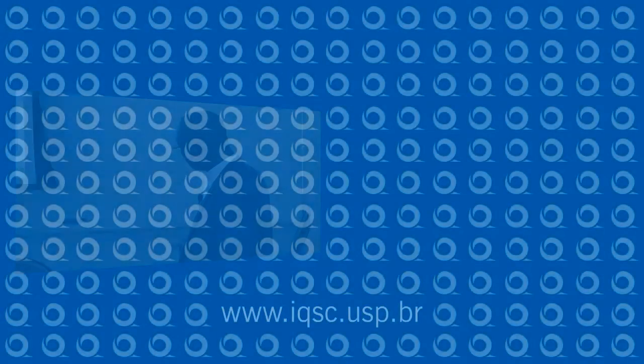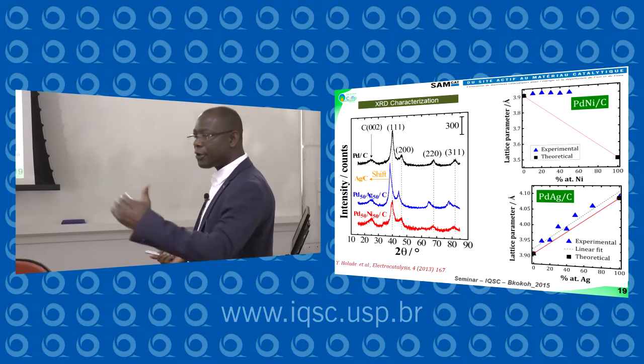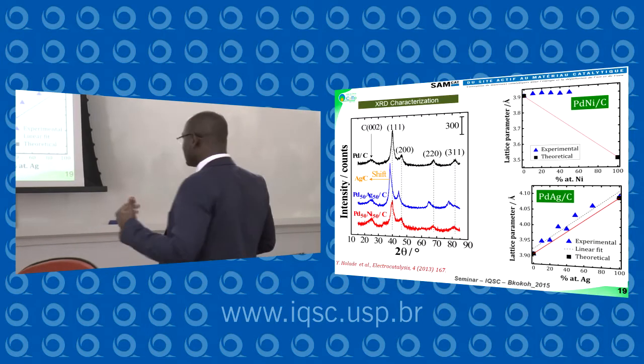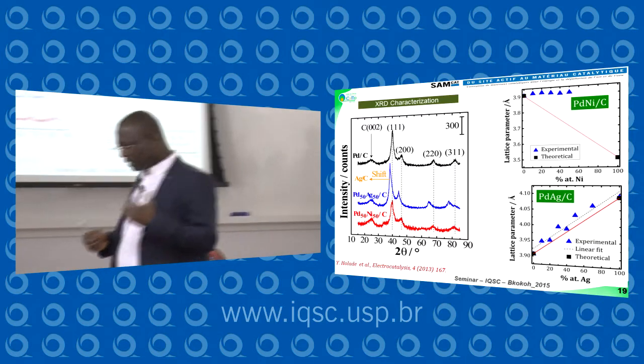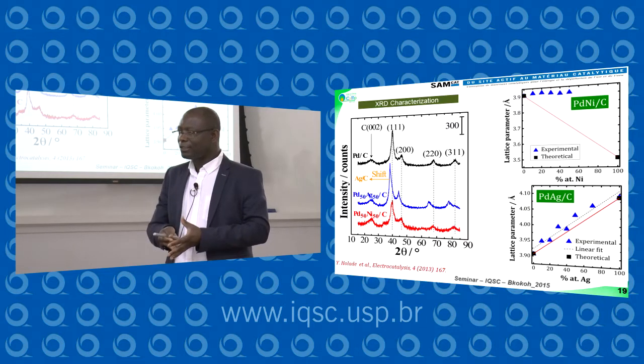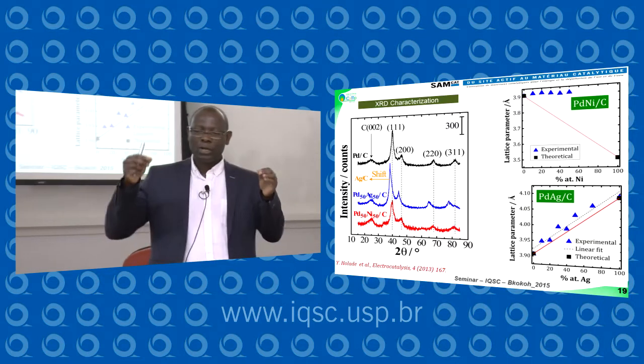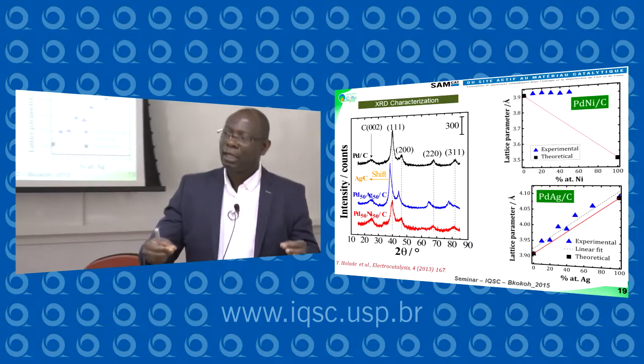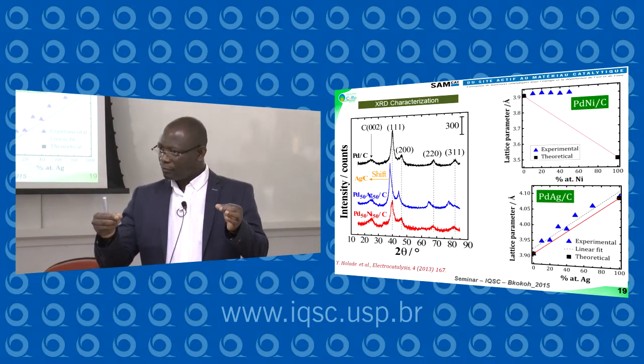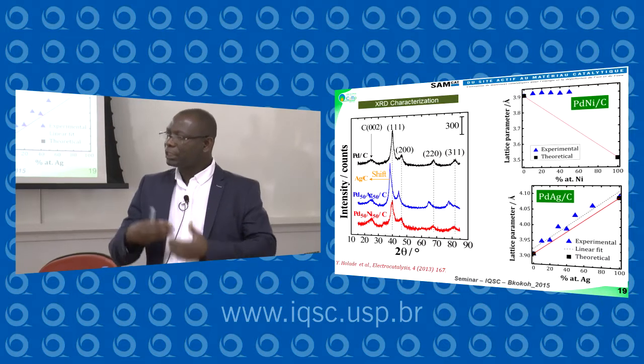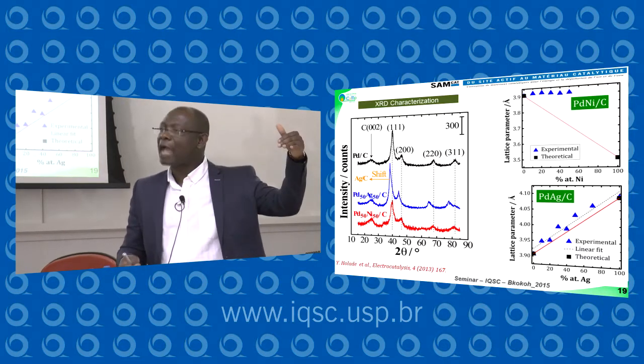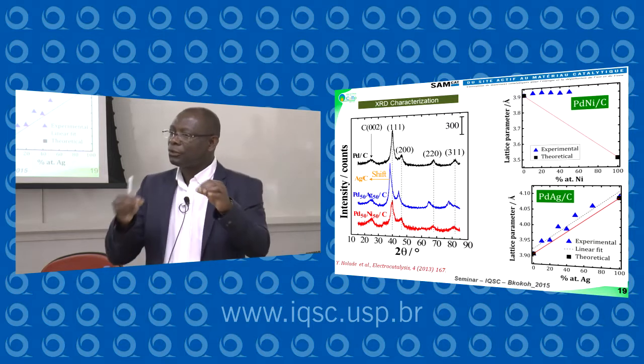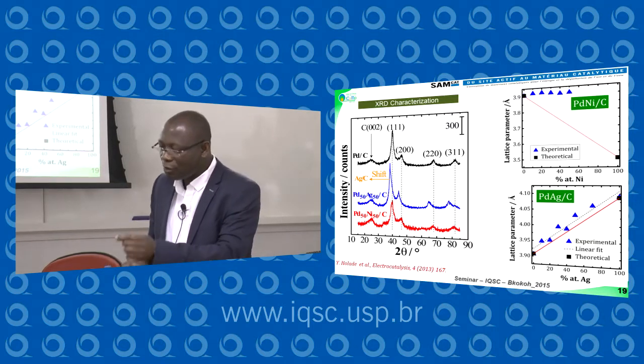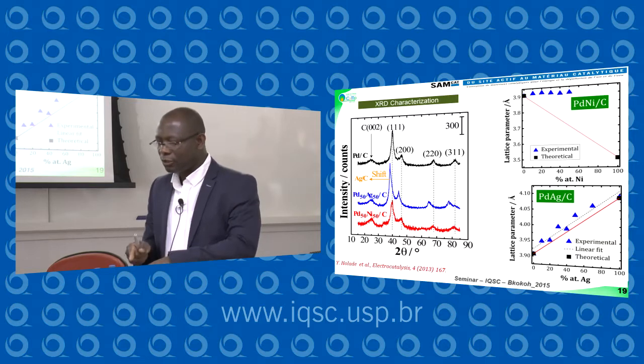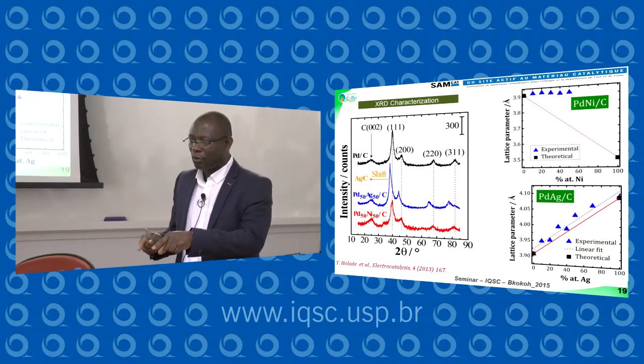And this is a theory. And the experimental values are higher than the theory. We explained that there is a problem during the synthesis. This means that when you use sodium borohydride, this precursor gives you bubbles of hydrogen. This means that the first nanoparticles of palladium catalyze the decomposition of borohydride.